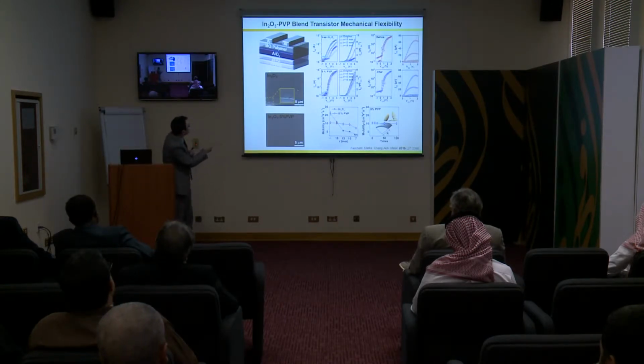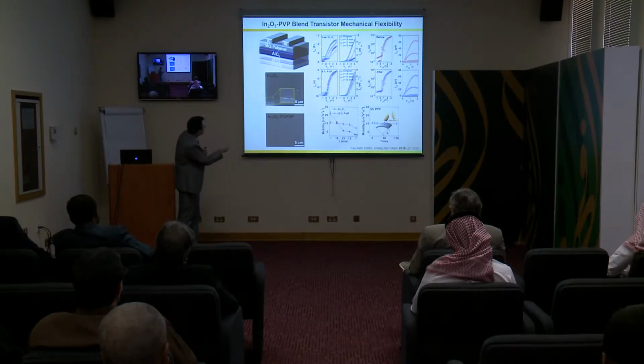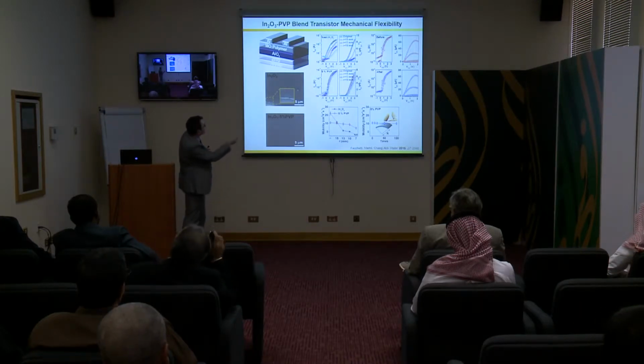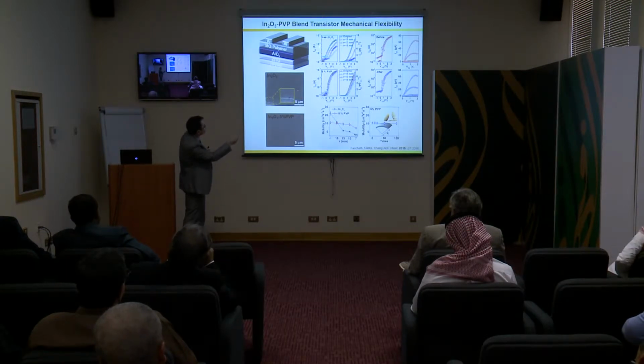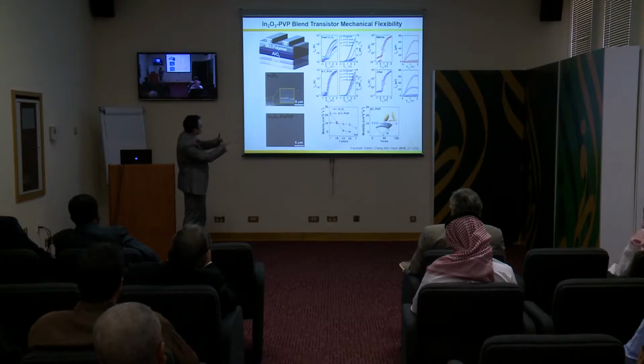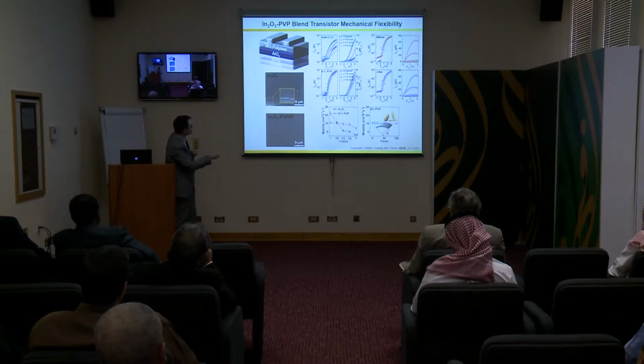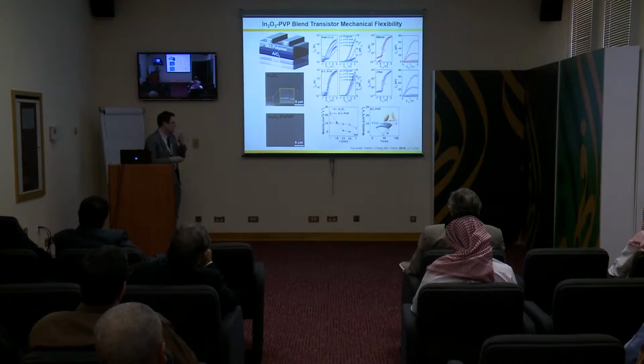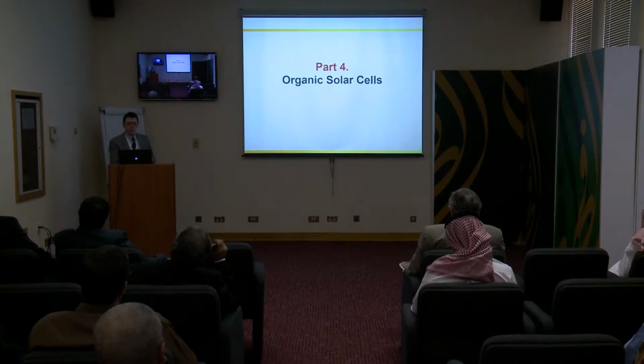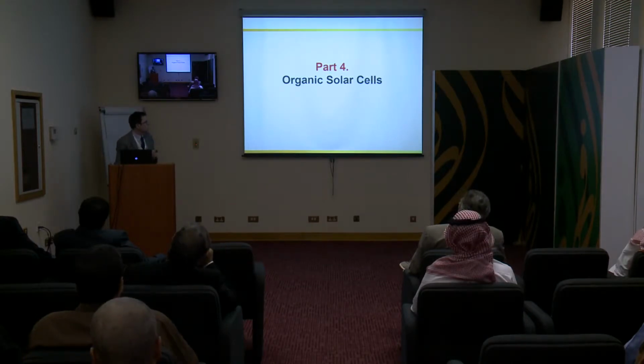If you use the matrix alone, which is polycrystalline, and you start bending, it's a little difficult to see, but you start forming cracks in your film. And this cracking results in a dramatic decrease of the current in the current-voltage plots because of crack formation and propagation. Instead, when you start doping with this insulating polymer, because of the amorphous nature, the variation of the mobility is much, much more contained. Okay, so it's a quite new, interesting way to make amorphous phases using metal oxide.